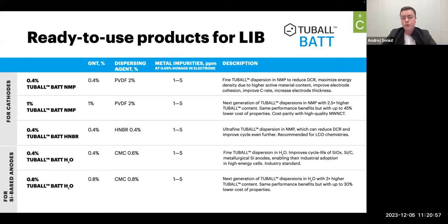Today we are offering 0.4, 1%, and 0.4 dispersions in terms of concentration of TUBALL for the cathodes. The first two dispersions contain PVDF as a thickener, and the last one contains HNBR as a dispersing agent to achieve a finer TUBALL dispersion in NMP. For water-based, for anodes, we are offering water-based dispersions: 0.4 TUBALL, 0.6 CMC, and 0.8 TUBALL, 0.8 CMC. The dispersions with higher TUBALL concentrations, 1% TUBALL BATT NMP and 0.8% TUBALL BATT H2O, are our freshest products, which we launched to the market basically at the end of last year and this year.